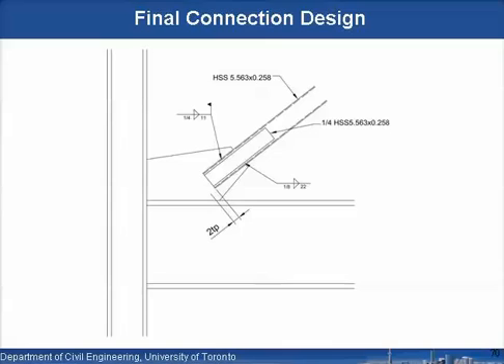Note that we've got this 2T gap here as well, so we can develop the plastic hinge in the actual gusset plate. And this is a very active research area at the moment. There are many different ideas on how to actually shape and proportion this gusset plate for even improved hinging here. But basically, one rule is not to over-design the gusset plate. Keep the gusset plate moderate, as thin as you can really, because then you won't transfer such large forces into the neighboring beam and column here.